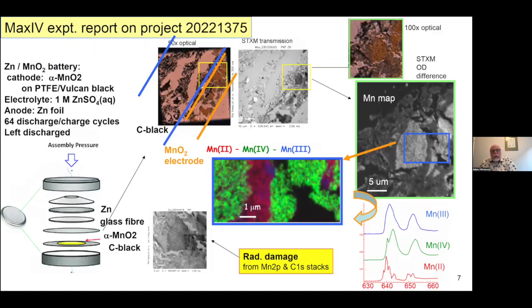Okay, so just a little summary. This is what I put back to the MaxIV as a report of this study that we did in 2023. And basically a lot of what you've seen, that we could characterize this degradation in terms of multiple oxidation states. The reason I'm showing this particular slide is that one of the challenges that you may encounter, particularly if you're looking at polymeric or biological materials, is radiation damage. The STXM X-ray absorption technique has very meaningful, significant advantages relative to electron microscopy, particularly electron microscopy with electron energy loss spectroscopy, but it still does radiation damage.